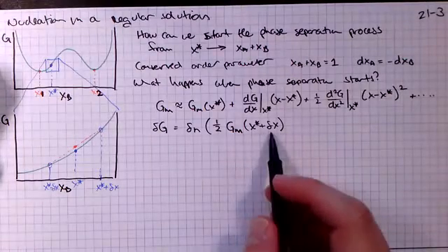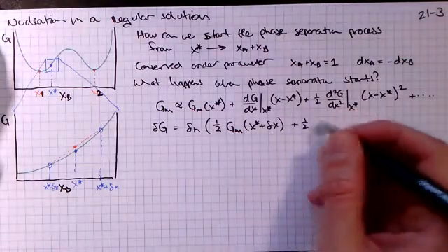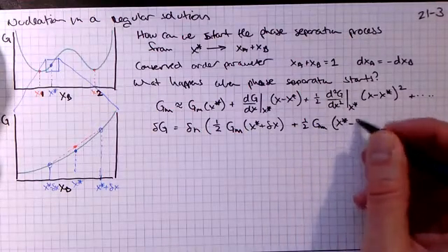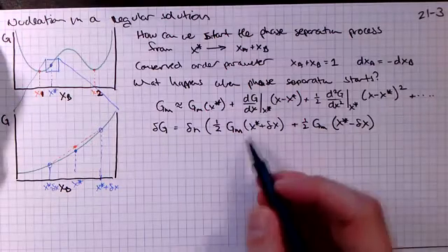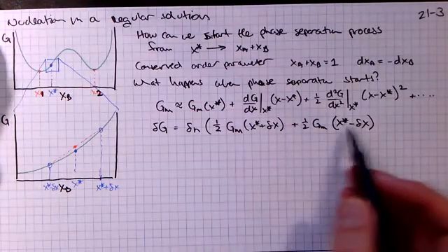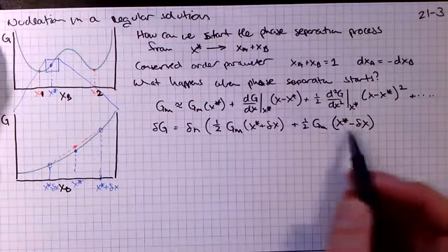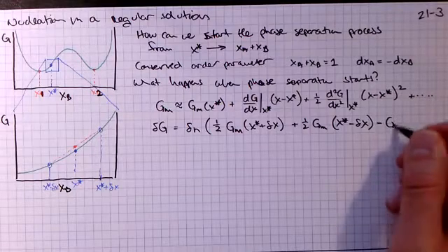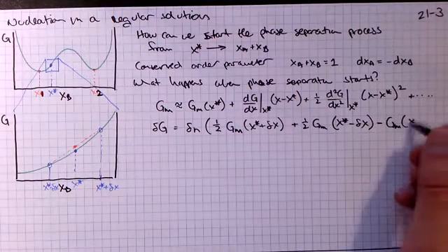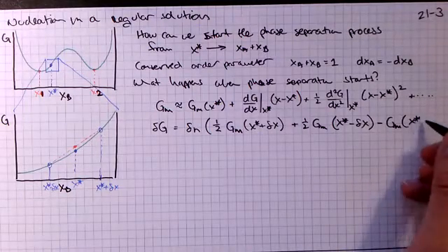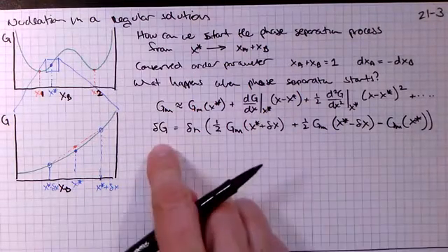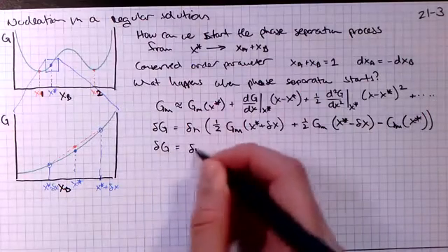We've increased X, plus 1/2 times the free energy per mole, and here for some portion of the material we've decreased the value of X. We've created an enriched region and a region that has less B, and then we have to subtract off the free energy per mole that we originally had, because we're getting the difference in the free energy. So the net fluctuation in the free energy is delta G, and now we're going to use our expansion.